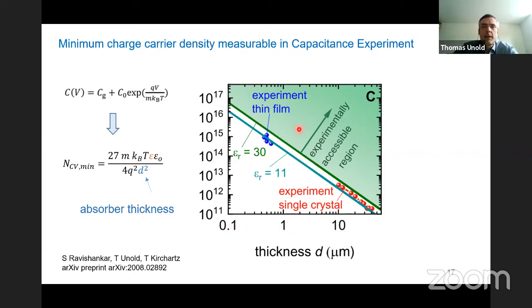And so the expectation is that this is the region you could access. So here, the charge carrier density is high enough that you can measure it in a given device. So you have a 1 micron thick device, so the charge carrier density should be above 10 to the 15. And this is the inaccessible area. And we plotted the data from the Science paper in here. And you can see that they just all fall on this minimum line, which shows that even a simple model can actually explain a lot of what's going on here. So this is a caution about using capacitance voltage profiling for getting charge densities or doping densities in devices.